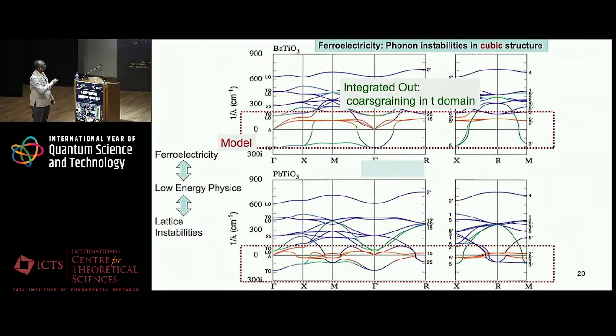This is the phonon dispersion of barium titanate and lead titanate, with phonon mode frequencies on the y-axis. The ones with negative values, which are the imaginary vibrational modes, determine the structural instabilities of these two crystals. And you can clearly see that they are quite different in their behavior. In lead titanate, you have unstable modes everywhere in the Brillouin zone, whereas in barium titanate, they stabilize in some parts of the Brillouin zone. So our focus is on these unstable modes.